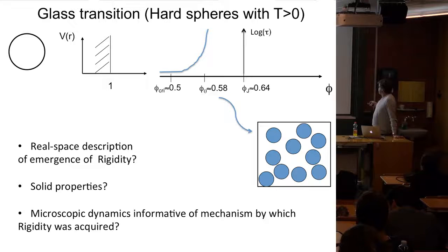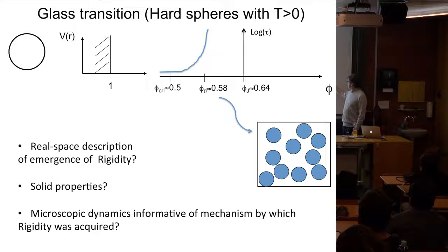But the surprising aspect of the glass transition is that if you look at the particles, in the structure nothing much seems to have changed. They were rattling around here and here, and you change the packing fraction a little bit, but the relaxation time changed a lot. So you have some kind of emergence of rigidity. You had a fluid, and here you really have a solid. So one question is, how do you think about those particles bouncing into each other suddenly forming a structure that allows them to carry a stress?